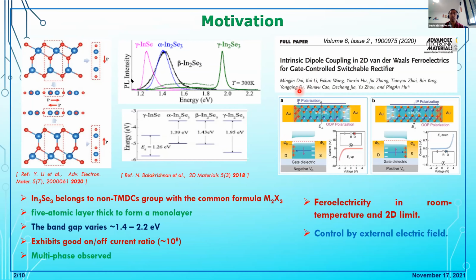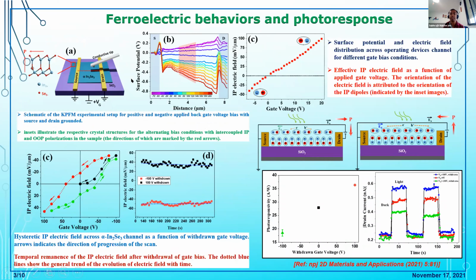Next, we jump to show some results of the ferroelectric behavior of this indium selenide. We use Kelvin probe microscopy to find this ferroelectricity instead of piezoelectric microscopy. Here we make field effect transistors, ground the source and drain, and then measure the potential between two electrodes. By applying the gate voltage, we see the slope changing from the positive to the negative side. From this, we can calculate the electric field in this channel, which is basically the derivative of the surface potential with the length. We found that the gate voltage can change the electric field between the electrodes, which is associated with the in-plane ferroelectricity. So basically, we are rotating the out-of-plane dipoles by applying the gate voltage.